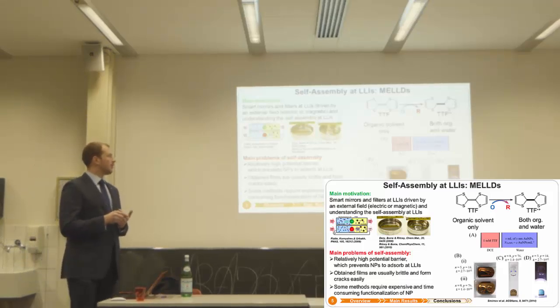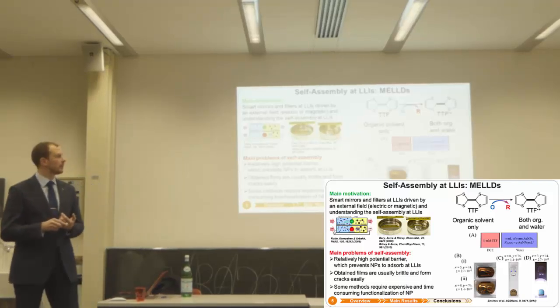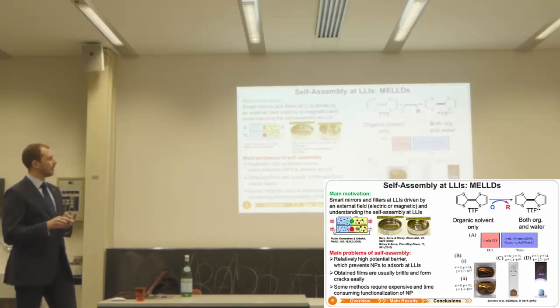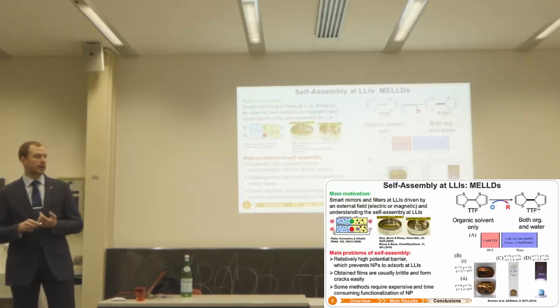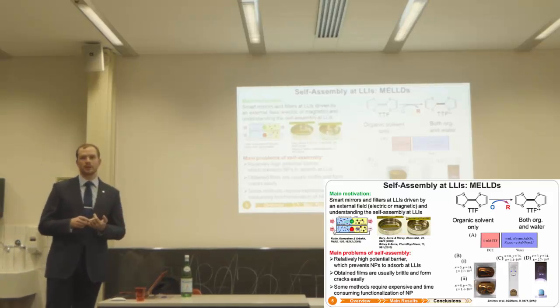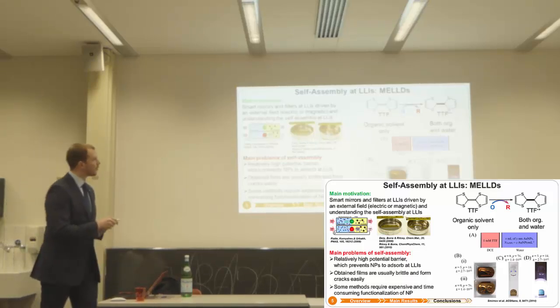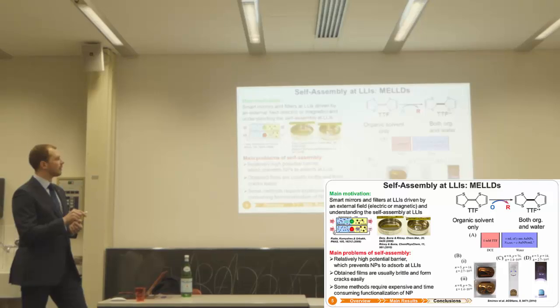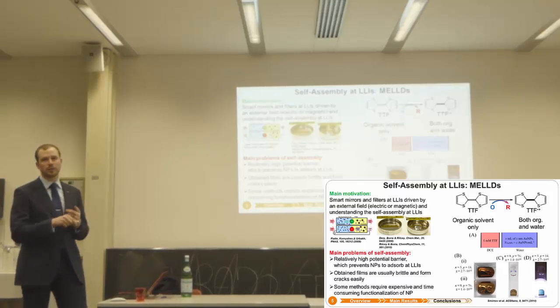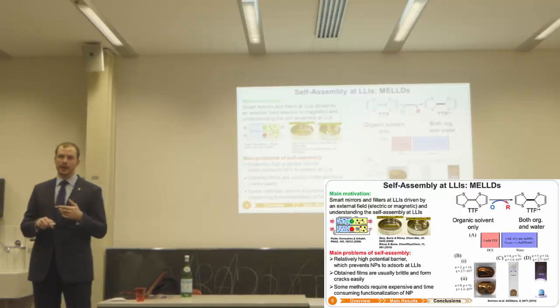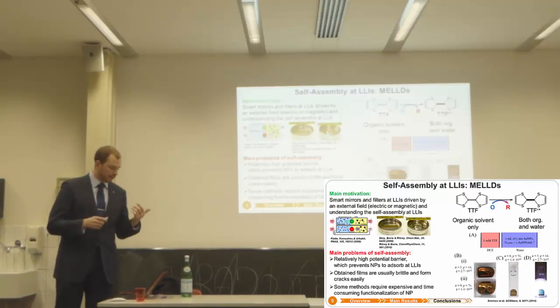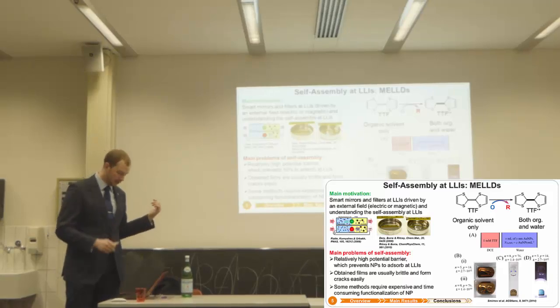How did we do that? We simply prepared a solution of TTF in a special organic solvent, DCE, dichloroethane, and added water-soluble gold nanoparticles. Then we simply mix them together vigorously and obtain such films. One interesting property of the TTF molecule I should mention here is that usually a neutral molecule is mainly soluble in organic solvent, but a charged molecule is soluble in both organic and aqueous phases. This property helps us to reach the result.